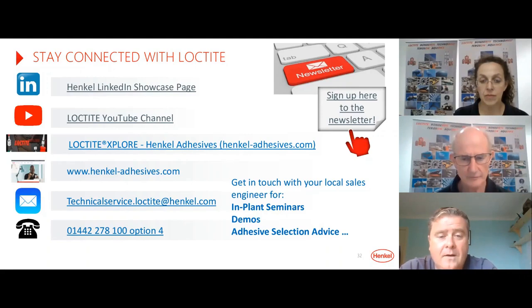Okay, and the final one. Once the adhesive is hard, can a full load be applied? How long do you need to wait before you can apply load? That really depends on the application. Julie talked about the two-part acrylics. They will get very good handling strength very quickly, within a few minutes. In that handrail bonding application, you need the whole thing to support itself very quickly. And in magnet bonding, again, if the magnets are magnetized, you don't really want to have to clamp the magnets for very long, because if they're bonded north-south, they will fly together if you don't have an adhesive curing very quickly.